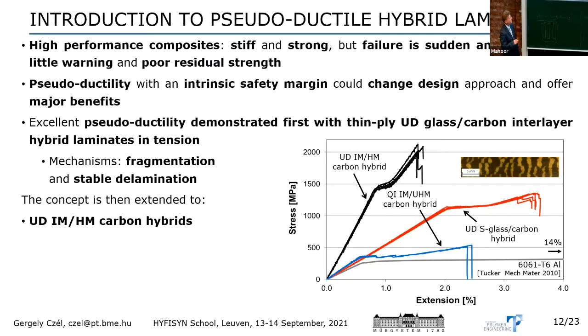Then we extended the concept to two different carbon fibers, intermediate and high modulus carbon. We hybridized. These were also unidirectional. Then we made a quasi-isotropic version where obviously the initial modulus was much lower, about 1/3, as we expected, but we used ultra-high modulus fibers to somehow boost it a little bit, and we still got pseudoductile behavior. And we also included a structural aluminum response for comparison.